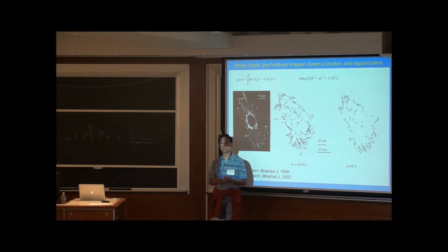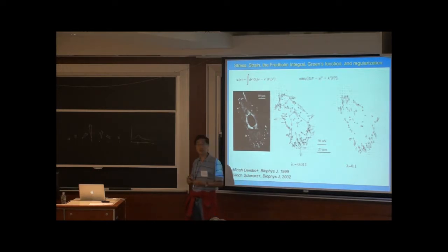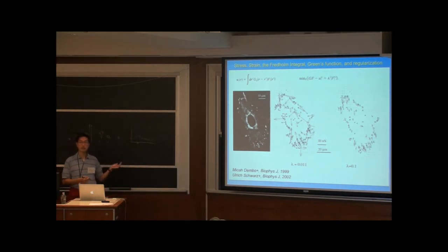So what people do is they say, I want it to sum to less than 10% of the total forces that I'm measuring. Then I feel okay. And some people will say, no, I'd rather sum to 1%. And you get different solutions based on that. So the bottom line is that this method, what you should realize is that the forces that you calculate are not determinate. There are many, many solutions to the same data set that you have in the beginning. Okay?